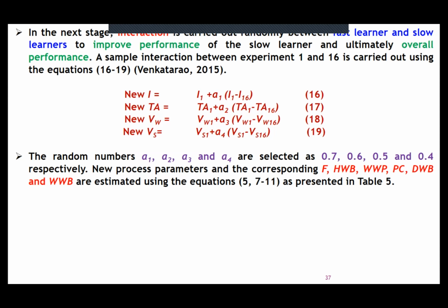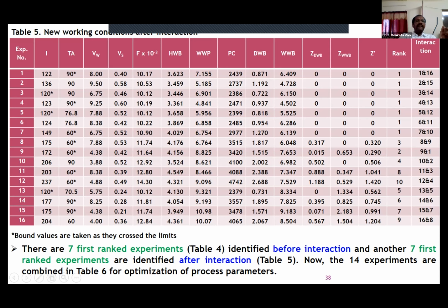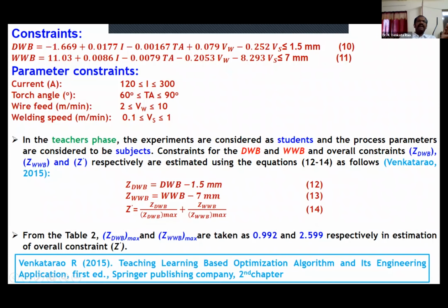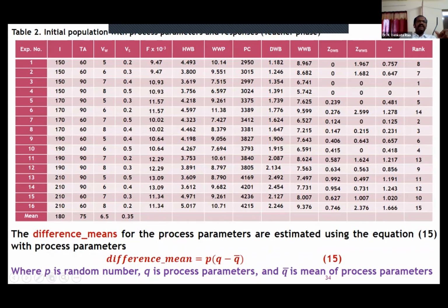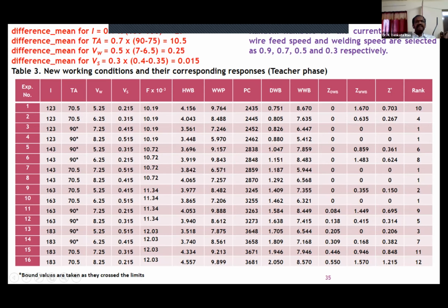Right. See, through the sequence 16, 17, 18, 19, new process parameters are obtained for the 16 experiments. So these are the new ones. See, somewhere we are seeing star marks, 90, 90. As I told you, see here, 120 star mark like that. The current should always be less than 120, and for this torch angle also we gave the bound values, parameter bound values. If the values cross this, only the bound values are to be taken. That's why star marks represent the bound values. When they cross that limit, that upper value or lower value will be taken.